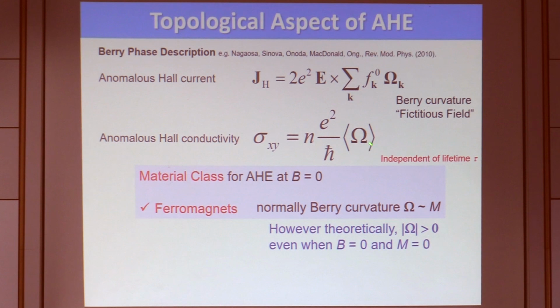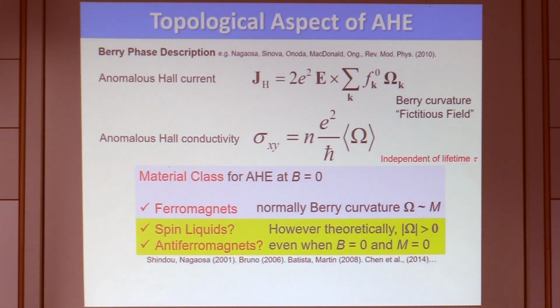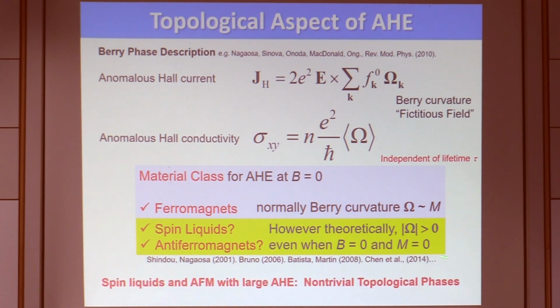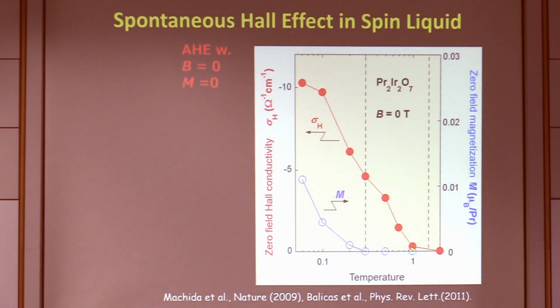But this theory also tells us it's actually driven directly not by magnetization, but by Berry curvature. Therefore, in the absence of magnetization at zero field, you should be able to see a large anomalous Hall effect, for example, in spin liquids or antiferromagnets. This has already been predicted by many theorists. This also motivated us to find those anomalous Hall effects in these non-ferromagnets or spin liquid antiferromagnets, partially also because it might lead us to find new topological phases, such as the Weyl metals. The first example of such a kind has been seen actually not in an antiferromagnet, but in a spin liquid.